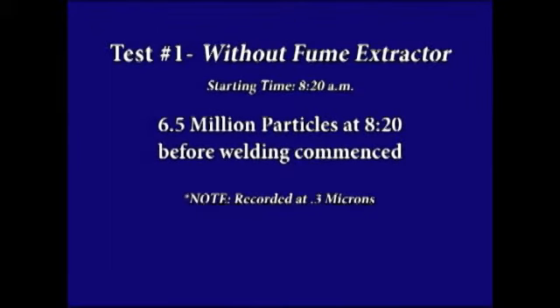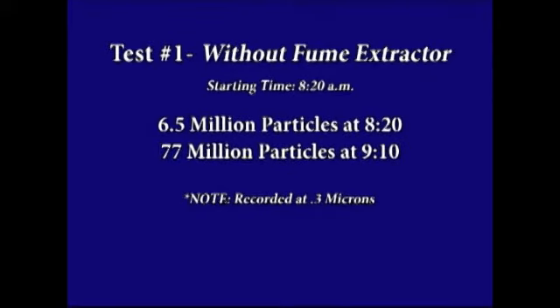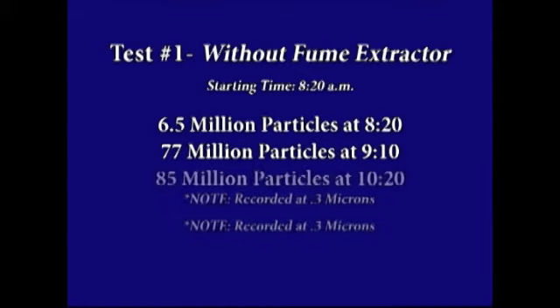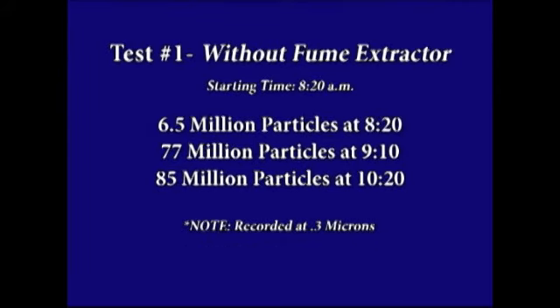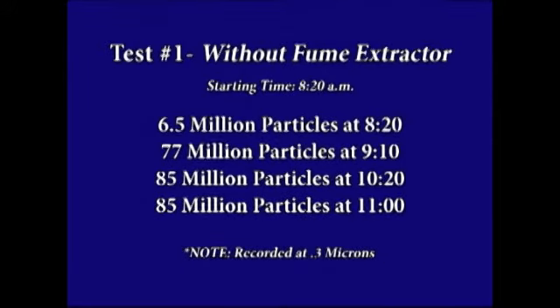As you can see, prior to welding commencement at 8:20 in the morning, the number of particles at 0.3 microns and larger was 6.5 million per cubic foot. With just a little over an hour of welding, the total particulate count in the ambient air rose to over 77 million particles. By 10:20, 2 hours after welding started, the total particulate amount rose once again to 85 million.